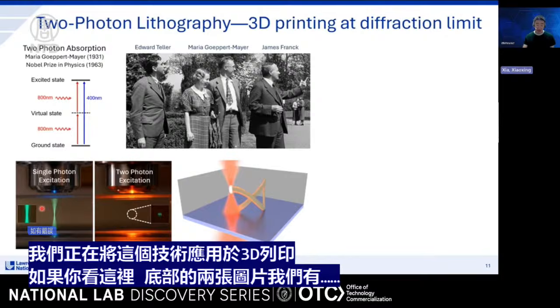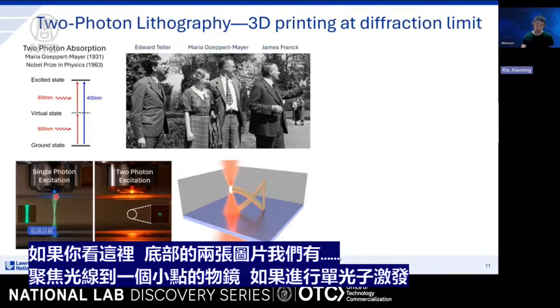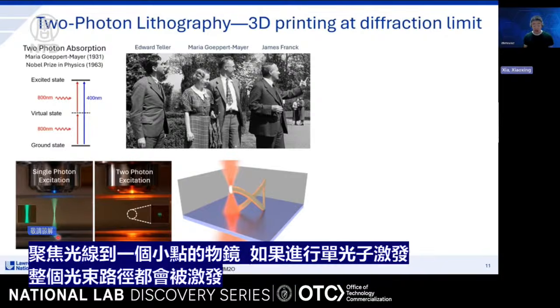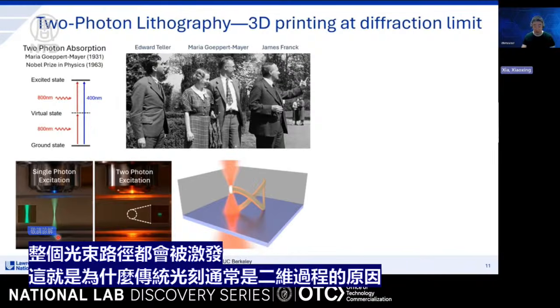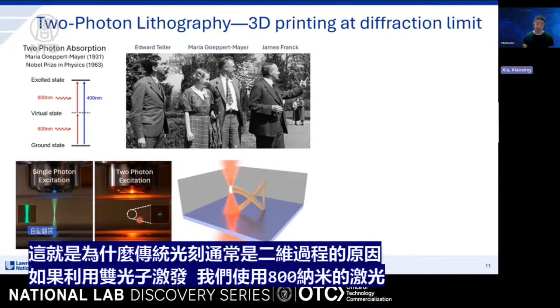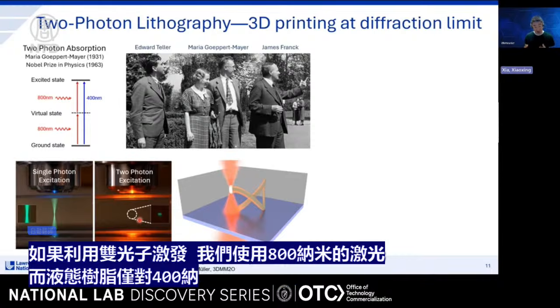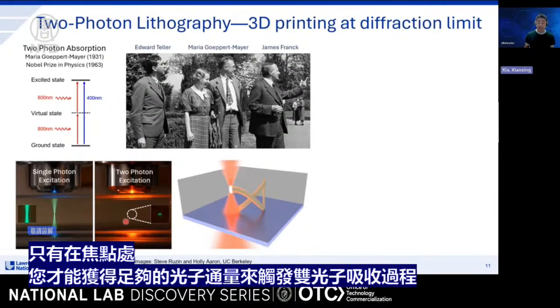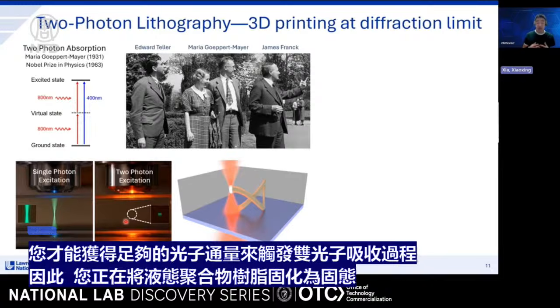And if you have single photon excitation, the whole beam path is excited. This is why traditional lithography generally is a 2D process. If you leverage two-photon excitation, we're using an 800 nanometer laser, and the liquid resin is only sensitive to 400 nanometer light. So only at the focal spot can you have enough photon flux to trigger a two-photon absorbing process. So you're curing that liquid polymer resin into a solid polymer.